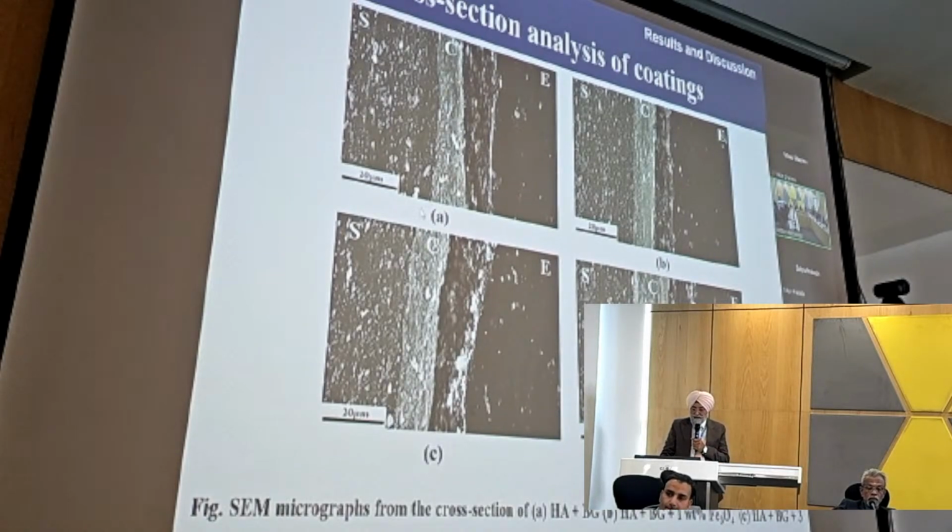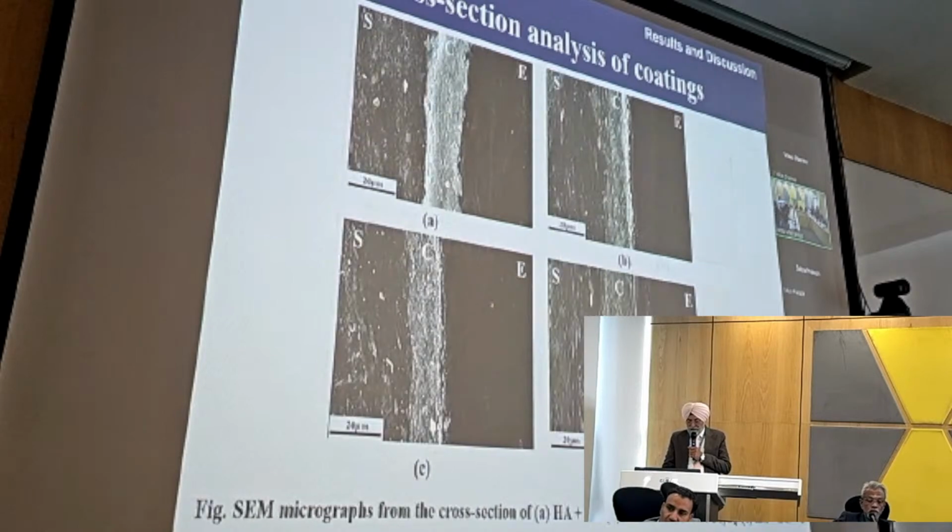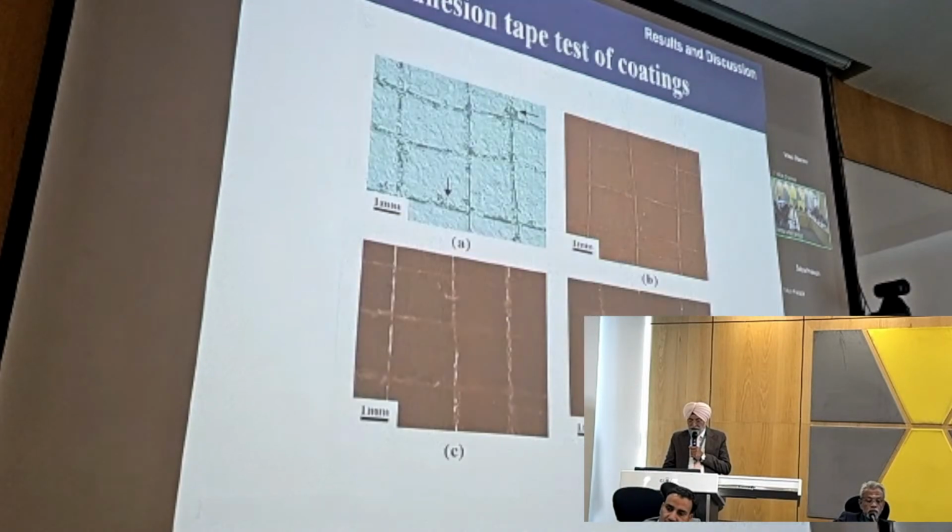When we obtain the coating, you can see uniform coatings of around 10 micrometers. This is also one of the advantages of this type of system. You will have a uniform coating. Otherwise, when we are spraying, this is one of the major challenges if you want to coat uniformly. Again, for the other type of alloy, we make an adhesion test for all types of coatings, and again,